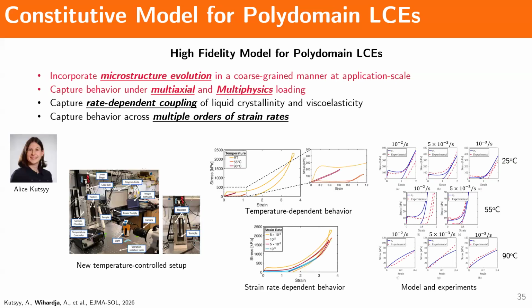Here in the lab, we did that by creating this new temperature-controlled setup for our LCE. We have a regular tensile setup, and then we enclose it in a temperature chamber, to be able to give us a full set of data for the temperature-dependent behavior, as well as strain-rate-dependent behavior for quite low strain rates, so quasi-static strain rates. This gives us experimental data that is temperature-dependent, and we can compare the experiments and the model and see that they roughly match each other. This is work that I have done also with Alice, who is an undergrad in our lab.